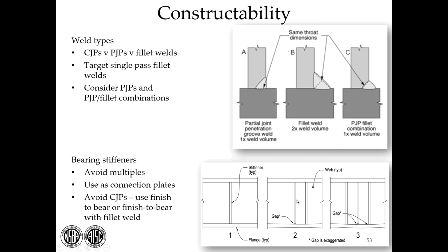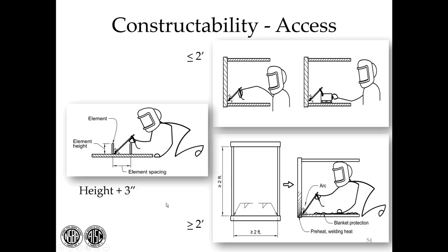For example, multiple bearing stiffeners. If you attach a bearing stiffener in one location, you have to use a lot of fuss to make sure you have contact. Then when you attach your second bearing stiffener, sometimes this will open up, so you have to come back and remediate that. Then when you've got them both ready and you come back with the third, you might then introduce a gap at the first ones. So we go into detail about why you want to avoid this. And in this particular situation, if you have jacking stiffeners near a bearing stiffener, we recommend you use a partial depth jacking stiffener.